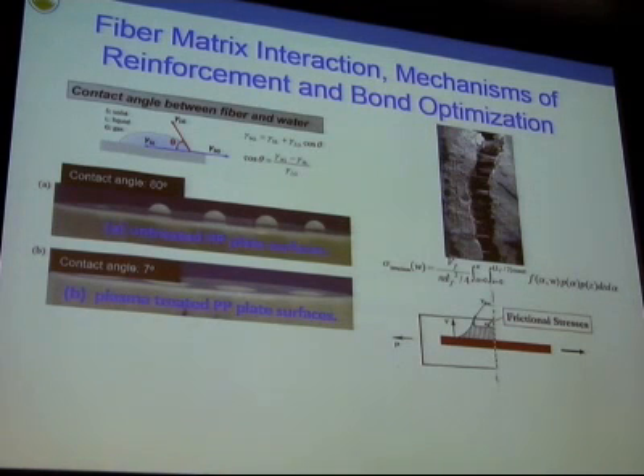And again, a fair bit of work that's been done here and in other places, generation of models, is on the surface chemistry itself. If you look at any particular fiber, it would have a very high contact angle with water. What we're trying to do is coat these fibers, thereby reducing the contact angle, which means that the fiber becomes highly hydrophilic. And when a fiber becomes hydrophilic, it will absorb a lot more energy, with a better bond. You can see these polypropylene materials which have had a treatment with plasma, which can reduce the contact angle quite substantially.